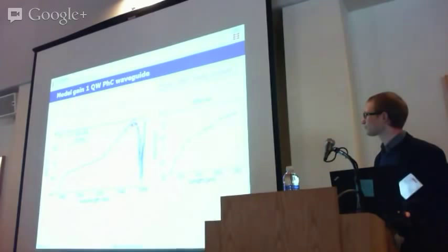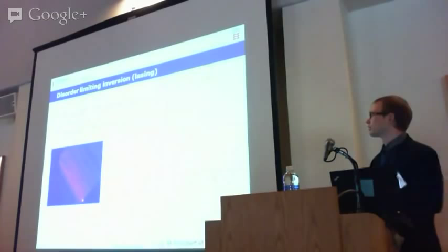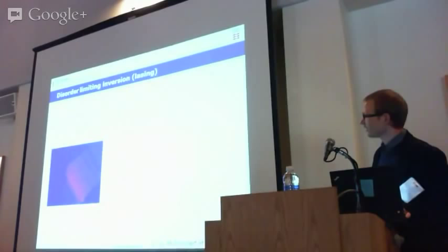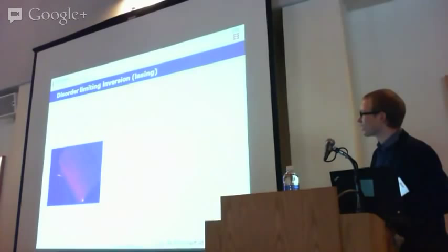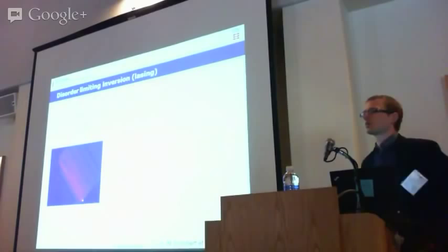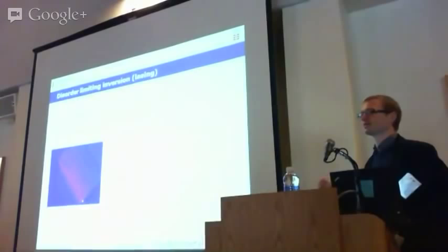So in principle it works, but in practice there are quite a lot of issues when you try to do this. This is an example of looking from the top of these photonic crystal waveguides, at different pumping lengths. What we can see is that we have these bright spots here. There can be two things: it could be simply that we have some scattering that scatters upwards, or it could be that we have a laser there. And in practice, we actually do have lasers.